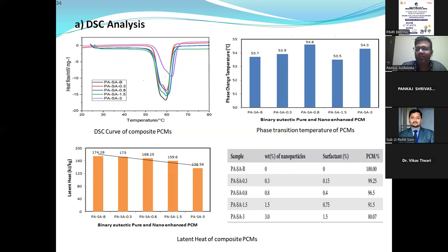But here is a drawback of the incorporation of nanoparticles: it decreases the latent heat capacity. And why is that? Because during the phase change, the pure PCM is involved in the phase change process, but the nanoparticles are not involved in the phase change process. Therefore, the latent heat of the system decreases. The latent heat of the nano PCM decreases as the concentration increases.